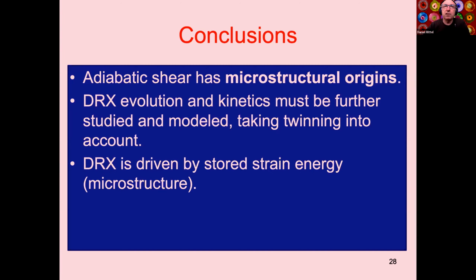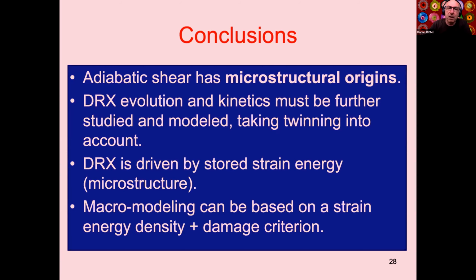Dynamic recrystallization, in fact, is driven by the stored energy because, as noted by Taylor many years ago, there's a limited amount that you can input in a material before something happens. And this stored energy, like fracture, is, we believe, the thermodynamic driving force for the phase transformation that locally softens the material. And something that we did and we still do is macro modeling based on the strain energy density and damage criterion. I will not discuss that for now. And that ends the first part of my talk.